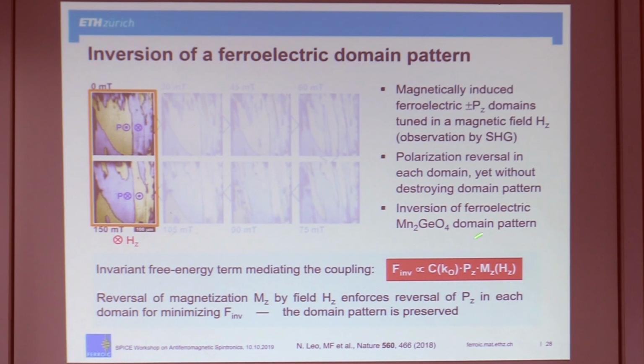But it boils down to this. So there is an energy contribution. It couples to a coefficient times a polarization, namely the polarization of this state here, this ferroelectric polarization, times the magnetization you induce with your magnetic field. So if you now take a magnetic field and you flip the magnetization between plus and minus, you also have to flip whatever polarization state you have in order to keep the energy contribution negative. So the direct coupling, because this term is just a coefficient, when you flip the magnetization, the polarization has to be flipped as well. So by cycling your magnetic field, you reverse the polarization in each domain.